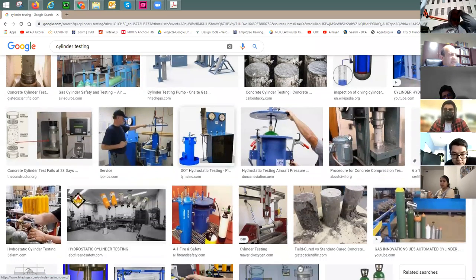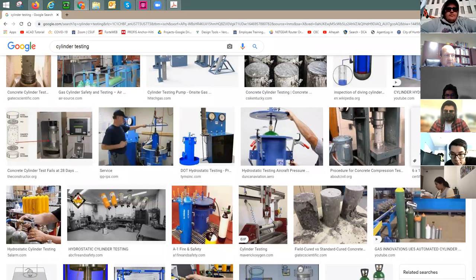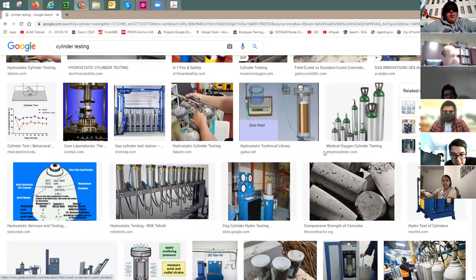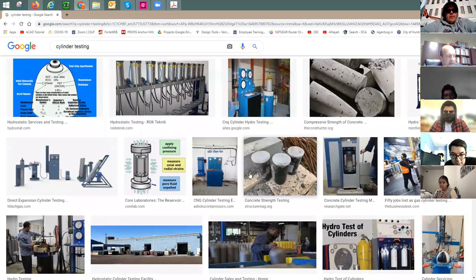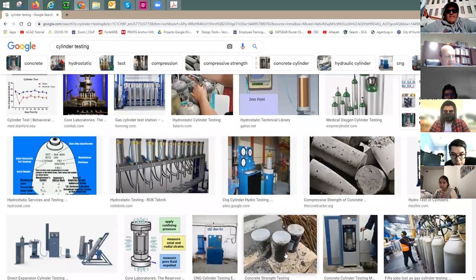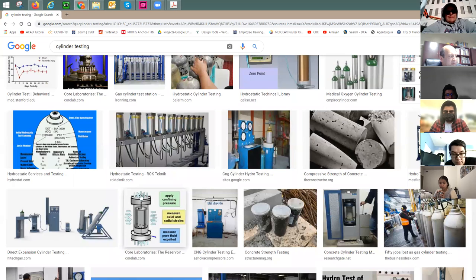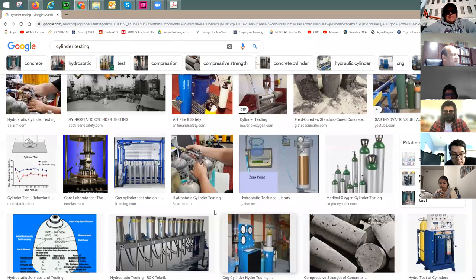Let me show you what happens in cylinder testing. We bring a mold — made of metal or plastic like regular PVC — fill the cylinder with concrete, top it, let it harden, and then strip the cylinder by cutting the plastic from outside. You put the concrete cylinder inside the testing machine and start to put pressure on it until it fails. You can do the stress-strain relationship if you have a means to measure the strains, or just take the maximum value the concrete attains, which we call f'c.